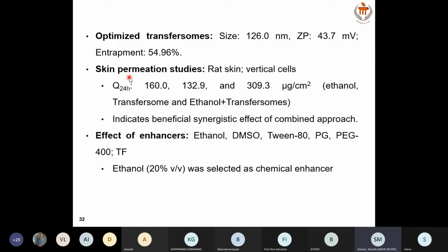So in case of skin permeation studies, the rat skin was used, and we used vertical type diffusion cells. We checked the amount of drug. Q24 is nothing but amount of drug permeated at the end of 24th hour. It was 160, 132, and 309 microgram per centimeter square in presence of ethanol, Transfersome, and ethanol plus Transfersome.